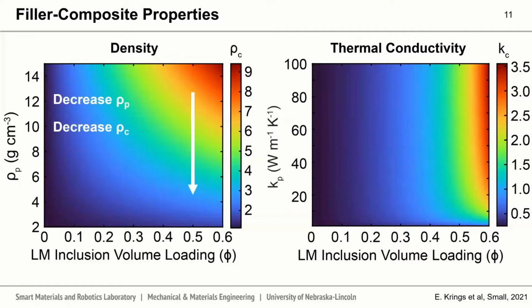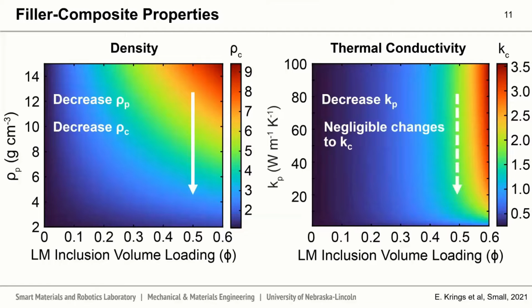So from this, we can see that if we decrease the density of the particle filler, we'll decrease the density of our composite, whereas if we decrease the thermal conductivity of our particle filler, we'll actually see a negligible change in the thermal conductivity of our composite. This offers us a new design space where we begin to optimize not only the functional properties of these composites, but also the density.